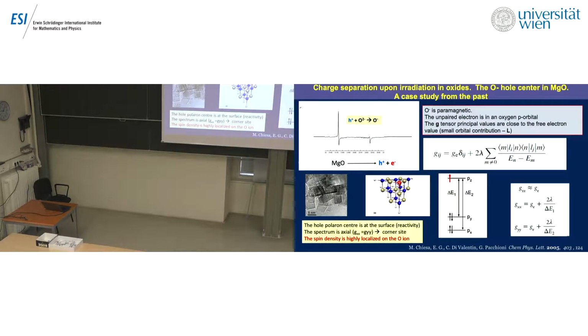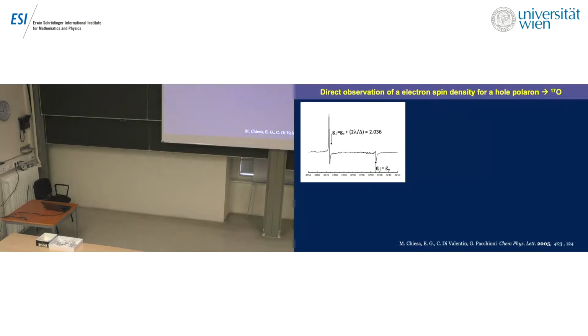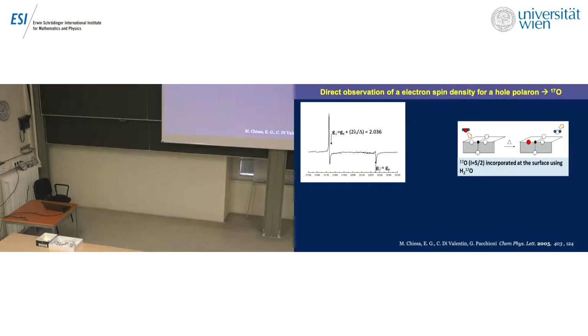The g value is derived with a perturbation approach. There is a deviation from the free electron value that is due to admixture of orbital contribution. But this is not the important point at this moment. The important point is that we did another kind of experiment and we used water containing oxygen-17, because oxygen-17 has a nuclear spin, and so we can have more information if you have a nuclear spin in the system, while normal oxygen-16 has zero nuclear spin.